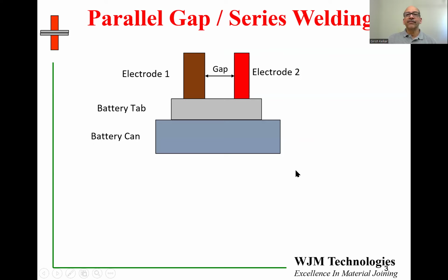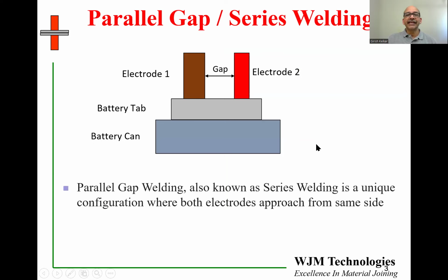Here's a schematic of the layout that I've shown in the previous photograph. Here we can see that we have the battery tab on the top, so this would be your nickel tab. The battery can is the surface of the can where you're trying to weld the tab. And there are two electrodes, electrode 1 and electrode 2. They are shown as different colors, indicating that the two electrodes can be of different material. They are shown of different size, indicating they could have different size. And they actually can also have different welding force.